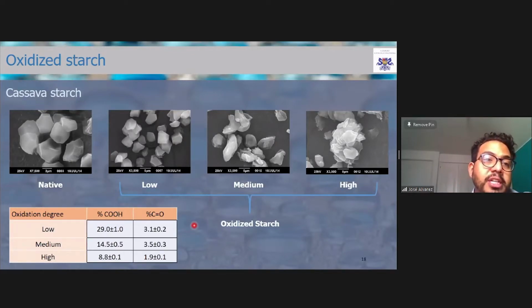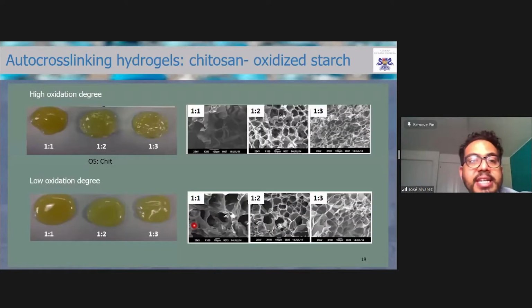So we went into modifying starches with sodium periodate, did all the characterization, and when we mixed a suspension of oxidized starch and chitosan, we were able to form these hydrogels.